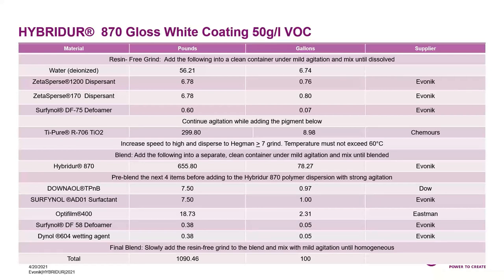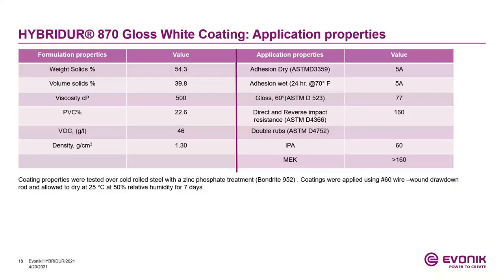And if it is required, we can add some rheology modifiers to get the rheology desired. And we do recommend certain rheology modifiers in the next few slides. So this gloss white coating typically is about 54% weight solids, about 40% volume solids, with a viscosity of about 500 centipoise, with a pigment volume concentration of 22.6% and 46 grams per liter VOC. And we tested the coating properties of this formulation over cold rolled steel with a zinc phosphate treatment. Coatings were applied using number 60 wire wound drawdown bars and allowed to dry at 25 degrees at 50% relative humidity for 7 days.